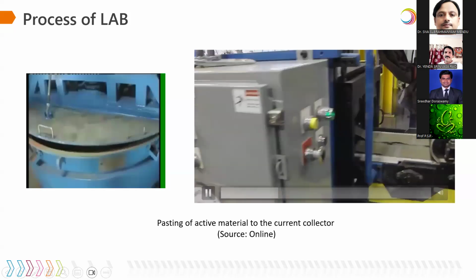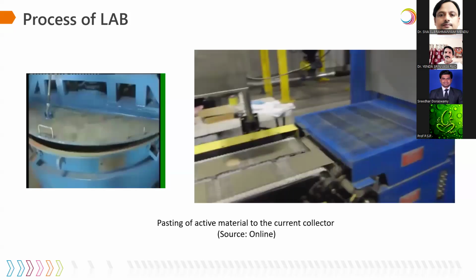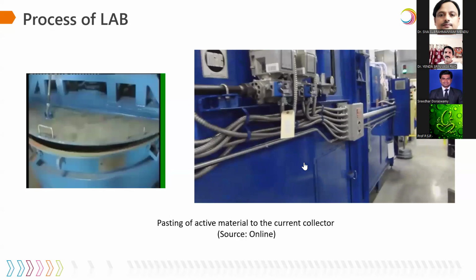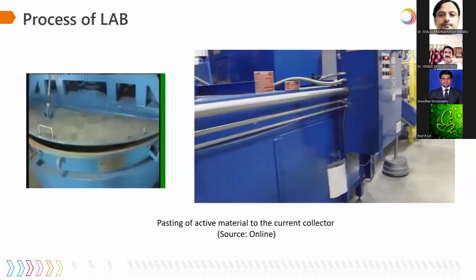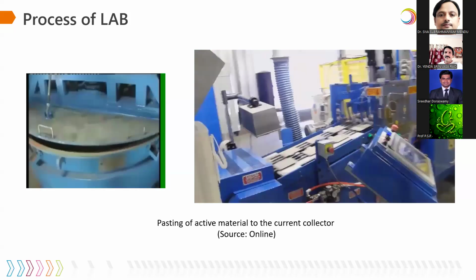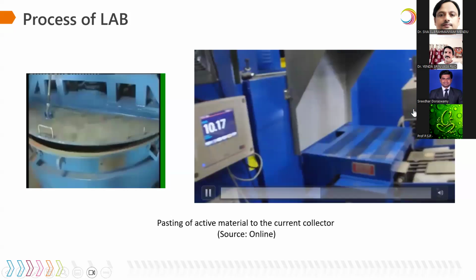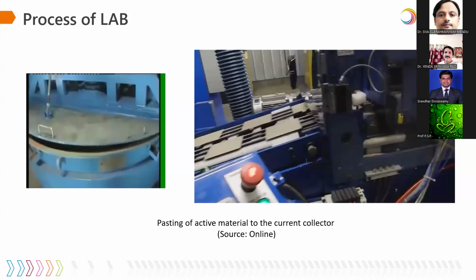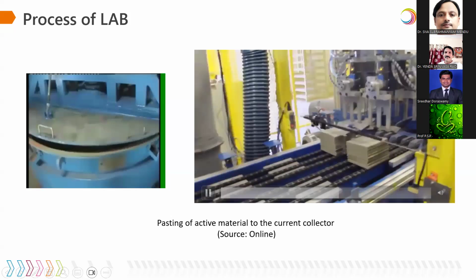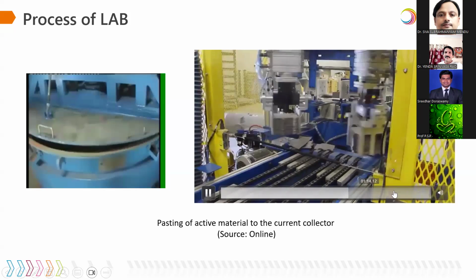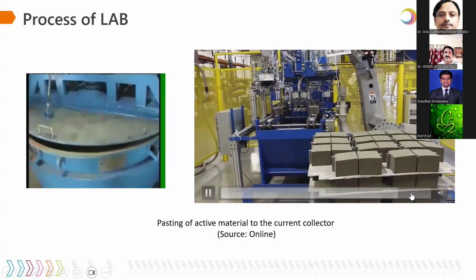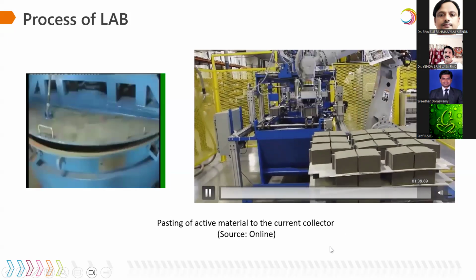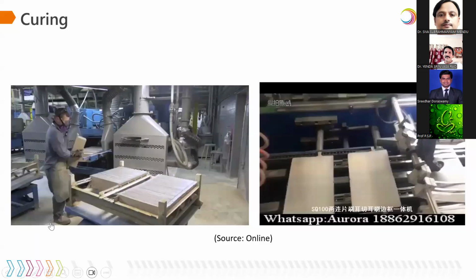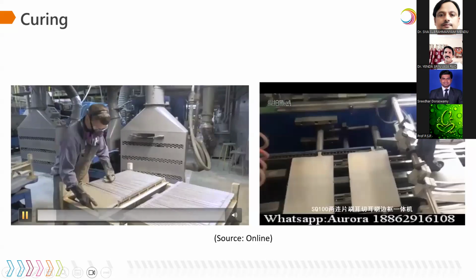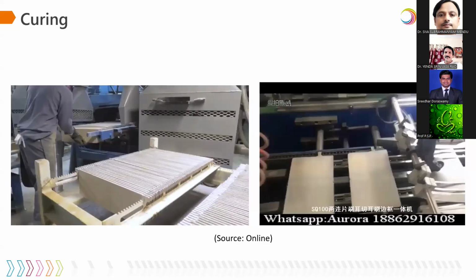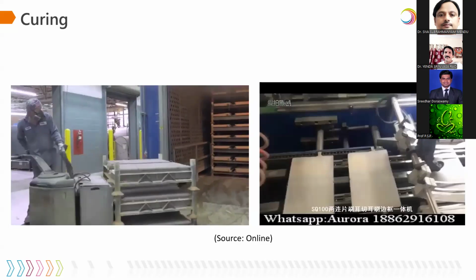The temperature is around 180 degrees centigrade to remove the moisture and the other contents in the plate. These are the flash dryers, and the plates are collected by the robotic arm. So these are the electrodes. After the pasting, it goes for curing. These are the big electrodes, used for telecom, railways, and industrial applications.